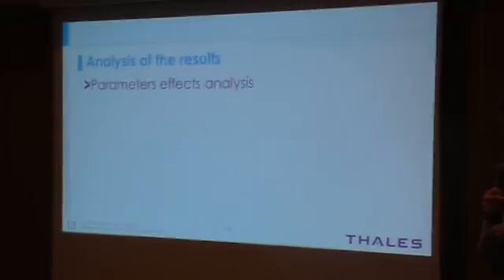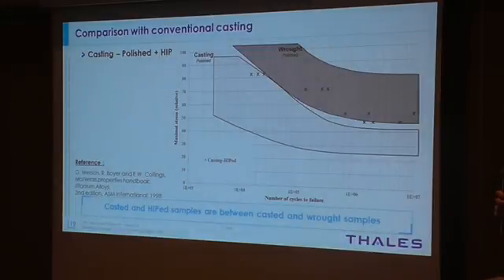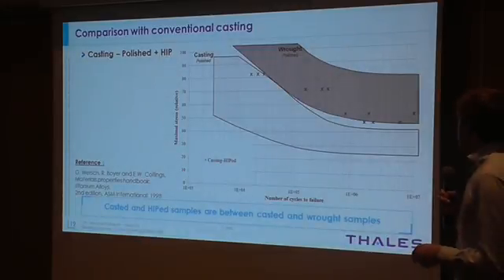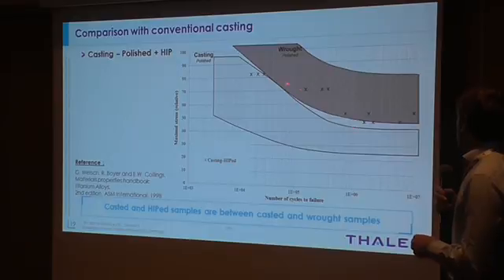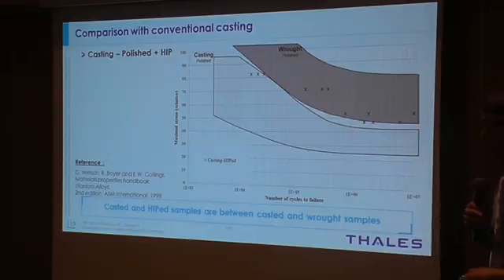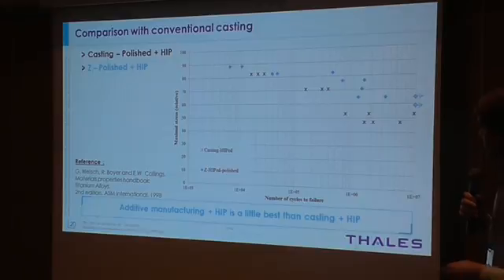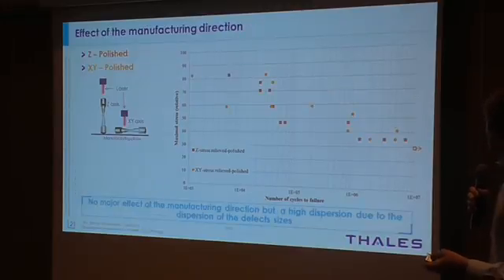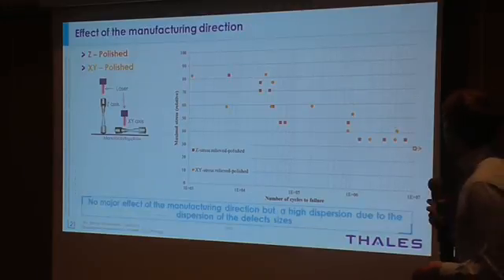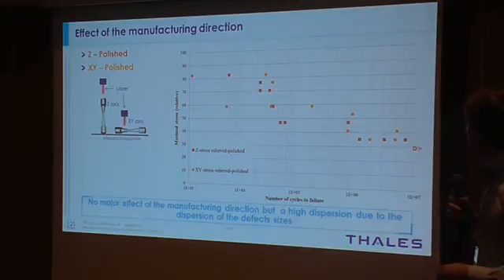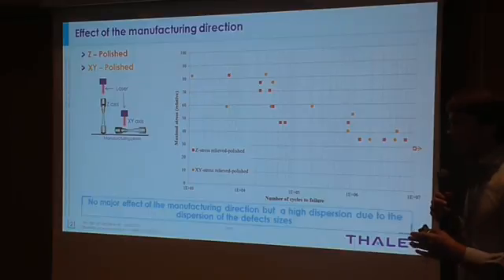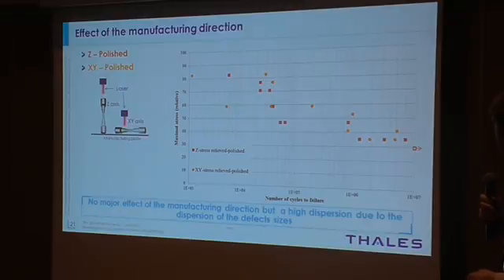So then we analyze the results to see the effect of the parameters. For the casted and HIP specimens, we are almost between casting and wrought processes. And when we compare with additive manufactured HIP specimens, we can see that they are a little bit higher. So it's pretty good for us. Then the effect of the manufacturing direction. So here we can see that the two directions are almost the same fatigue results.